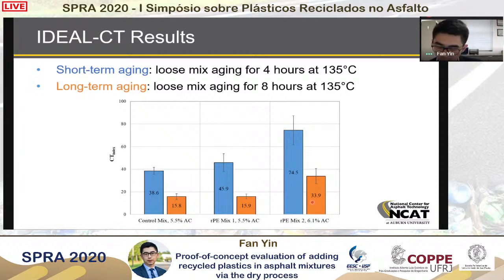at the intermediate temperature. This is a little bit surprising to me, because we know adding plastic is going to make the binder stiffer and have reduced relaxation property, which should have a negative impact on the fatigue or the cracking resistance. I think one of the reasons that can cause this result is because the IDEAL-CT test is highly dependent on the asphalt binder content. At this point, I'm still not 100% sure whether or not these tests can capture the presence of plastic in the mix. I think definitely more research needs to be done on this perspective.